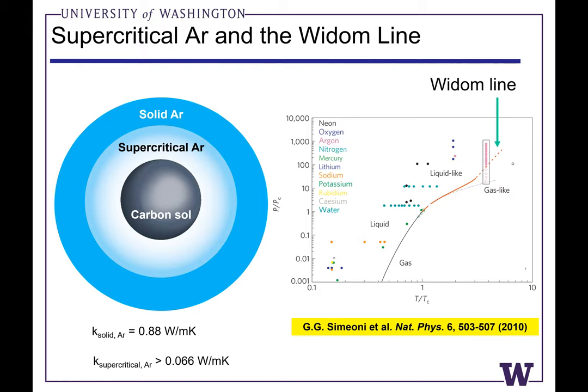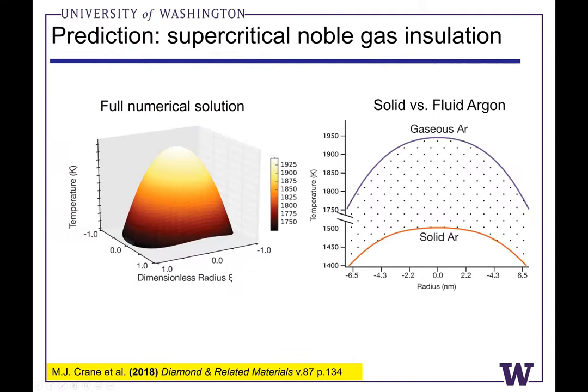We can take them to an electron microscope under high vacuum conditions, and the argon atoms are trapped as point defects in these materials. We can also compare the analytical calculations that we've made by solving this three-dimensional Laplacian, using a multi-infinite series approach to calculate these temperatures. And sure enough, if you drop the thermal conductivity by an order of magnitude, we can easily reach 2000 Kelvin in this sort of gaseous or supercritical argon phase.